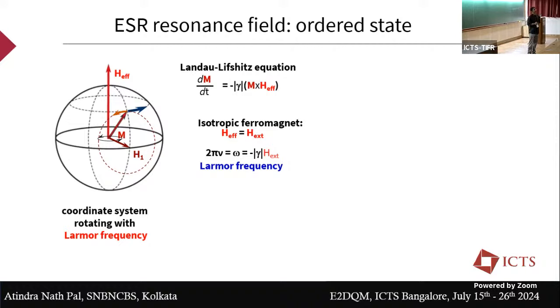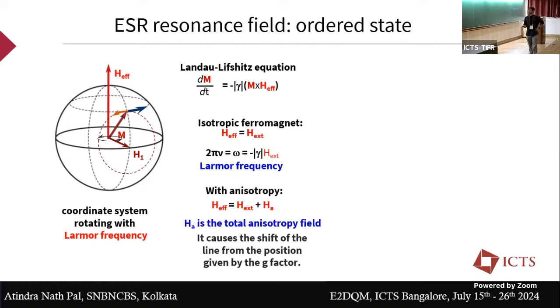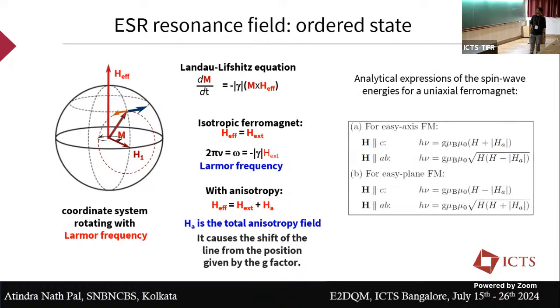Now, if you have some kind of intrinsic anisotropy in your system, what will happen? H effective will be equal to the external magnetic field plus the anisotropy field, right? So the resonance line will shift. Depending on the shift of the line, you can accurately measure the magnetocrystalline anisotropy in the system.